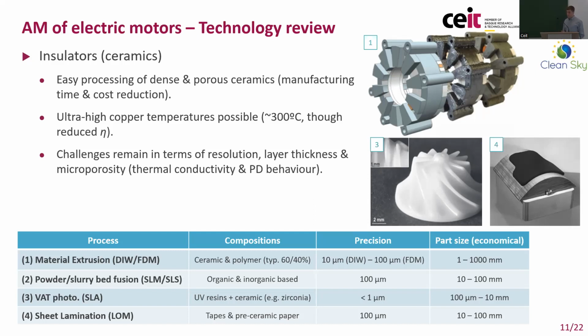So there are quite interesting prospects regarding the additive manufacturing of ceramic and insulator materials using additive manufacturing techniques, but quite a few challenges remain regarding the resolution and the precision of the components that can be achieved. Quite especially regarding the microporosity of these components, as this directly affects the thermal conductivity of the ceramic parts, and also the partial discharge behavior.